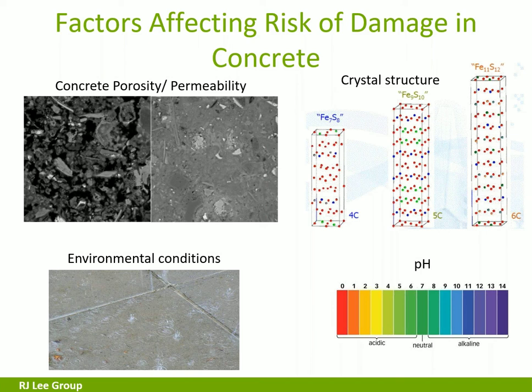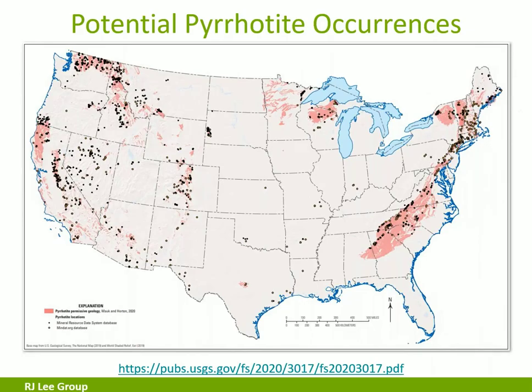So just last month, the U.S. Geological Survey put out a fact sheet, which can be found at the URL that I have listed there, and it created this map which only shows where the geology indicates the potential for pyrrhotite formation. And this is based on geochemical and physical processes of the geology of the region. This map, just to tell you, there's no verification or testing of aggregate in these areas to document that there is pyrrhotite present. It is just to show you where there might be.